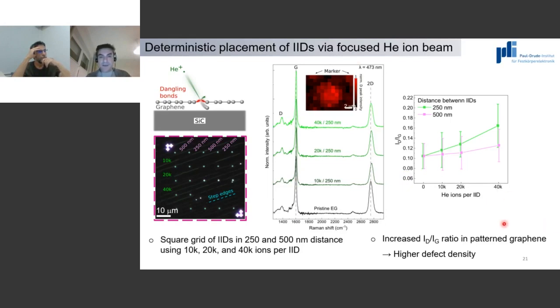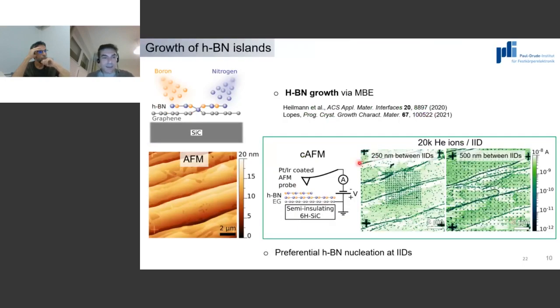And then the next thing is, okay, what happens when you grow HBN? That's what we got. Here I show you this AFM image where we have these markers in the corner and in the middle. I don't know if you can see here, but you can slightly see the pattern that we have. This is easily seen when we do conductive AFM. As I said, you come with a metallic tip and probe the surface, and you get information about the electrical properties, if you will.